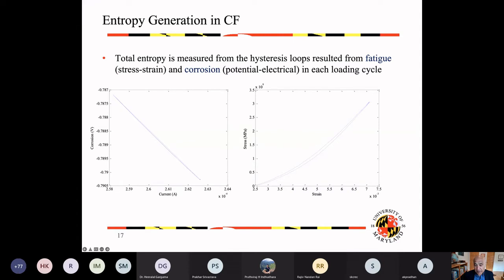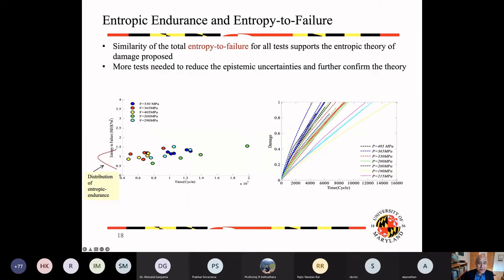For fatigue, it's a little bit more significant. You see the strain increases, goes to this point and comes down. Again, this shows one cycle of load, and the area confined inside is how much energy is dissipated, which then turns into damage. Once that happens, I can sum these two together into one unit, and that is called the entropy unit. Entropy is measured in megajoules per degree Kelvin per unit of volume, okay? So both of these energies, whether corrosion or fatigue, can be summed together.